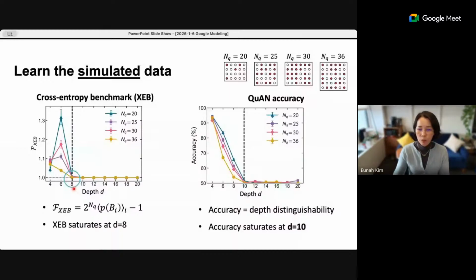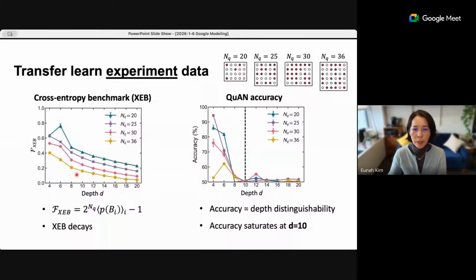When we then use the experimental data, when you try to compare experimental data to a classically simulated forward model using the cross entropy benchmark, you cannot really tell anything is happening at any depth, because the data is now very much ridden with noise. So when you compare the experimental data ridden with noise with a limited forward model, because our forward model tends to be limited by our inductive bias about a perfect system, it's hard to model a non-perfect system.